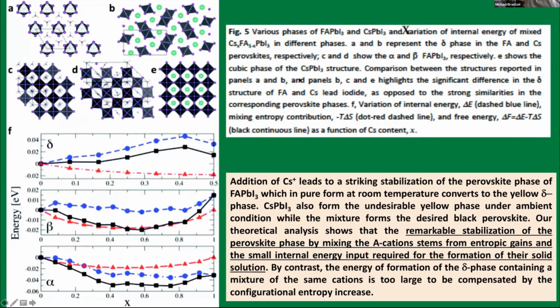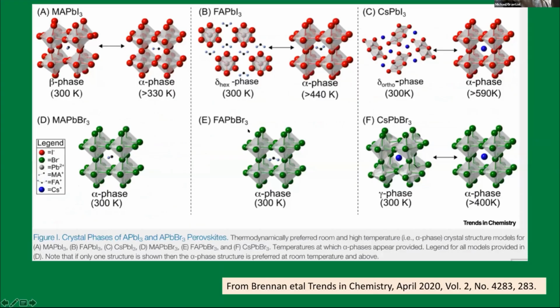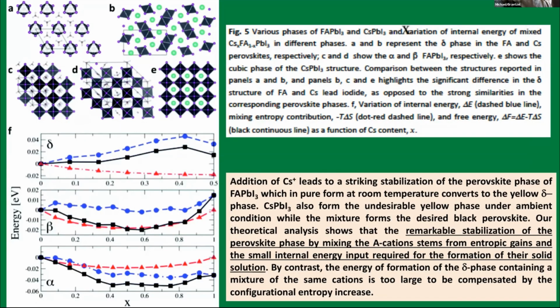And so the reason why this stabilization occurs, mainly the entropy of mixing is trivial. If you mix two cations, well, then the disorder goes up, the entropy goes up, and it helps you. But it's not the whole story. It's also the fact that you need a smaller internal energy input to form the solid solution, okay? And so the two effects together, here you can see this is the combined stabilization effect. And again, this is published, so we don't need to go into details. But that's a remarkable stabilization. And even today, to be honest, we still try to fully understand these phases, and some of them are metastable, they last for a long time. So it's still a kind of an enigma.